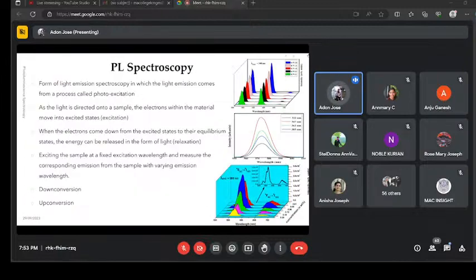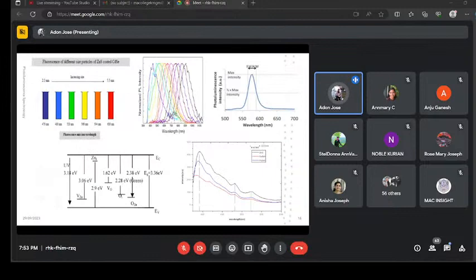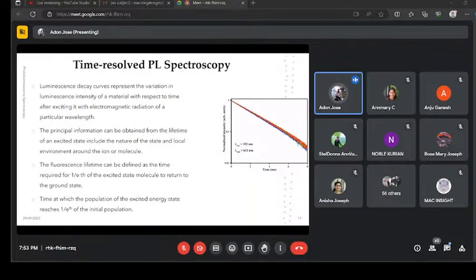Whenever we look at this diagram, we can see that there are two dominant peaks, which are observed at around 570 and at around 480 nanometer. These emission bands have certain significance, because one is from the yellowish region and the other is from the bluish region. Based on the materials which show these bands, we can construct materials having white light emission, which is the applicability of that type of materials.